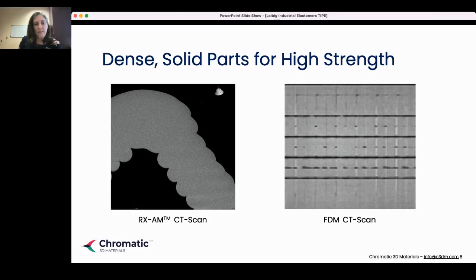And the important thing about these voids is that you can print a part with a material that has good base properties, but in the part itself, the voids can actually lead to failures and can cause a part to fail prematurely relative to the failure point of the material. And so the fact that we're able to make dense, solid parts is really helping us penetrate these industrial markets and move into industrial markets for 3D printing.